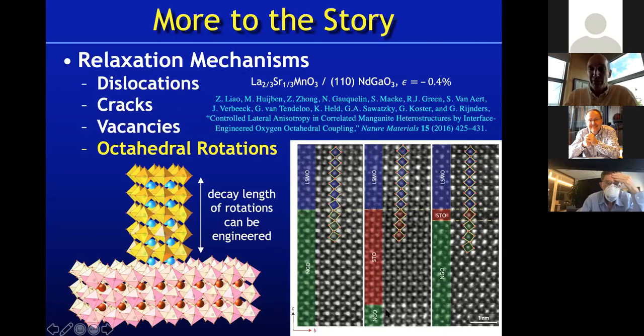They also looked at what happens when you put an intermediate layer, so starting from a neodymium gallate substrate, putting an intermediate layer of strontium titanate, which has in bulk no octahedral rotations. What they see is that in the strontium titanate, the octahedral rotations fall off from the neodymium gallate, eventually reaching no octahedral rotations, even though this is a fully commensurate film of strained strontium titanate. Okay, and then when they grow the lanthanum strontium manganite on top of it, there are no octahedral rotations that follow. The most dramatic case is over here on the right. A single unit cell of strontium titanate drastically damps the octahedral rotation decay length in this material.